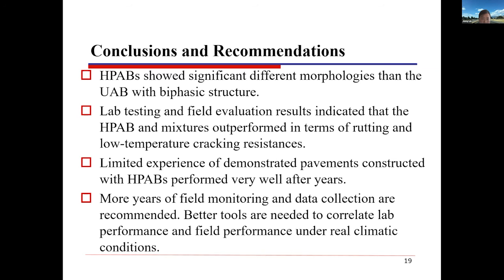Okay, so here are conclusions and recommendations for this brief presentation. HPABs showed significantly different morphologies than UAB, with a biphasic structure. Lab testing and field evaluation results indicated that HPABs and the mixtures outperform in terms of rutting and low temperature cracking resistance. The limited number of demonstration pavements constructed with HPABs performed very well after years. However, more years of field monitoring and data collection are recommended, and better tools are needed to correlate lab performance and field performance under real climatic conditions.